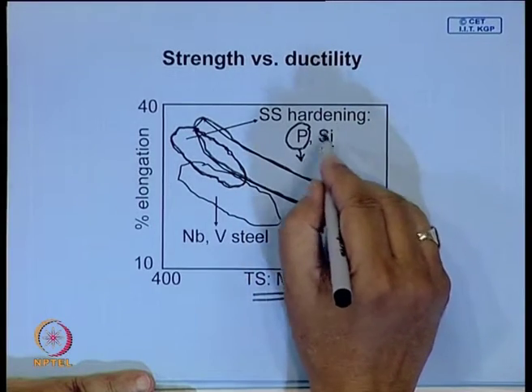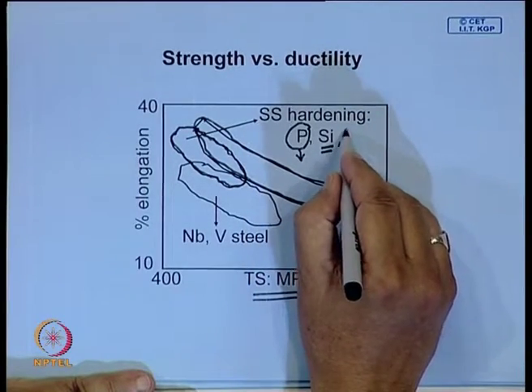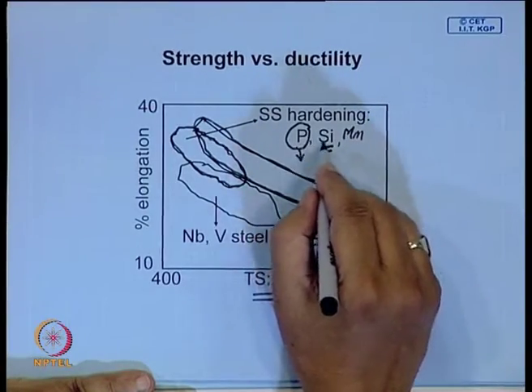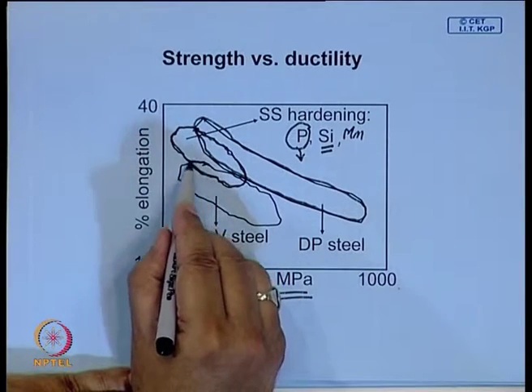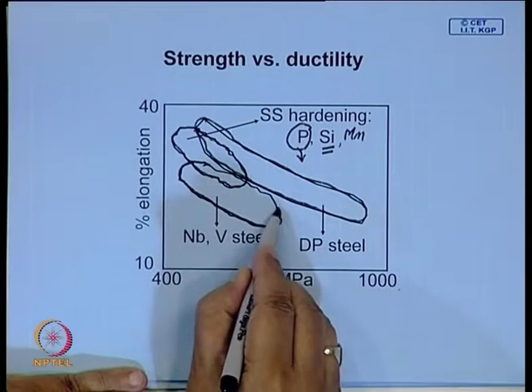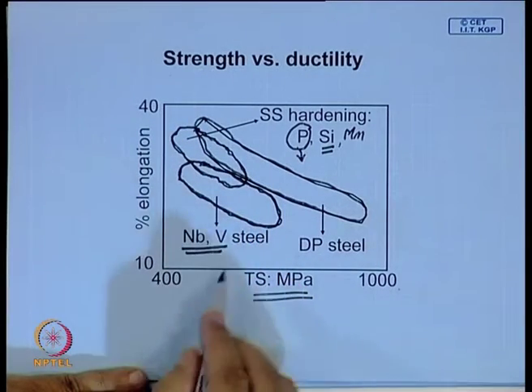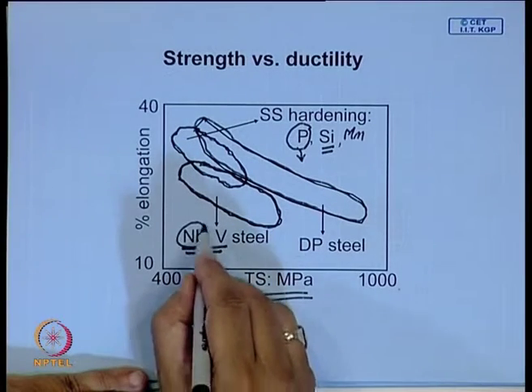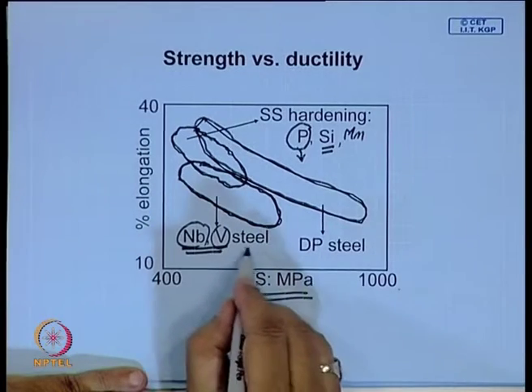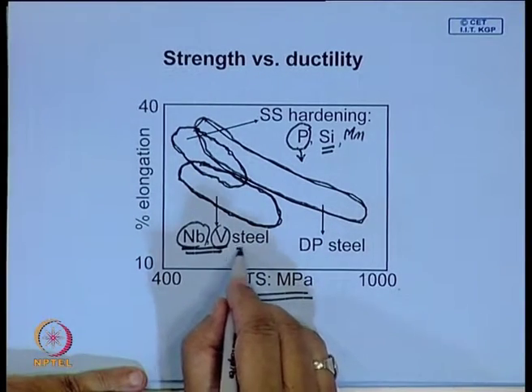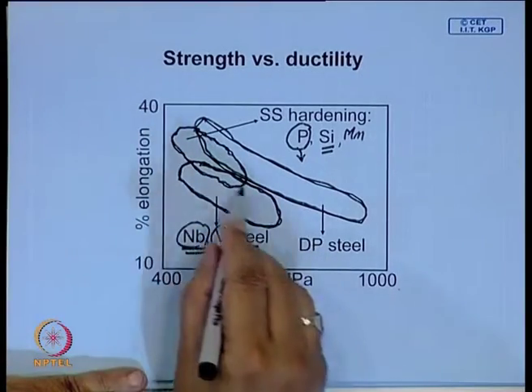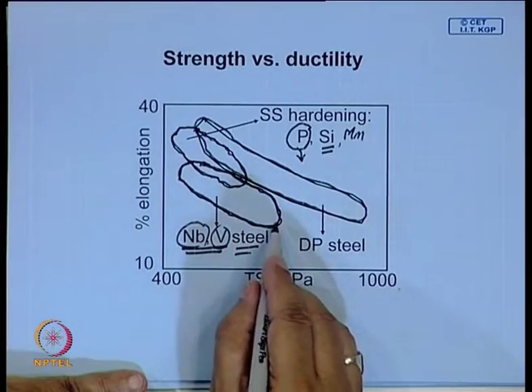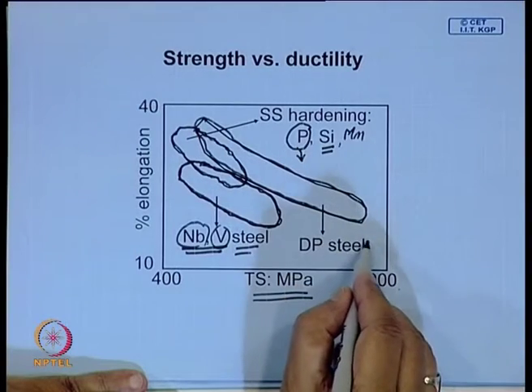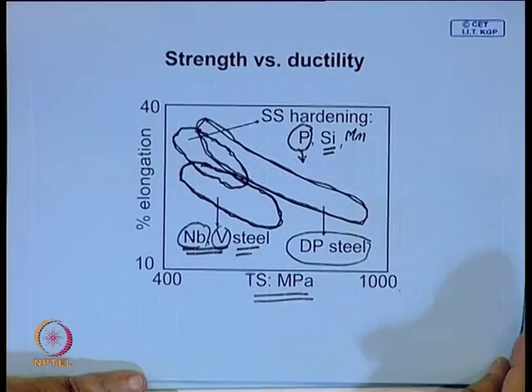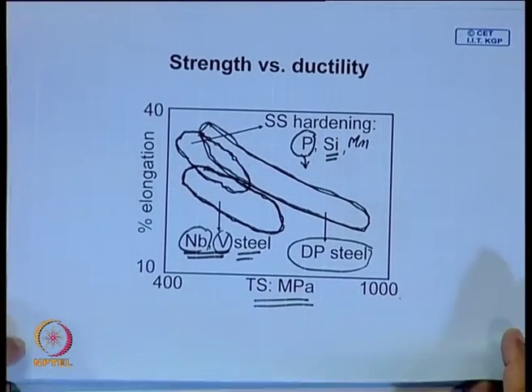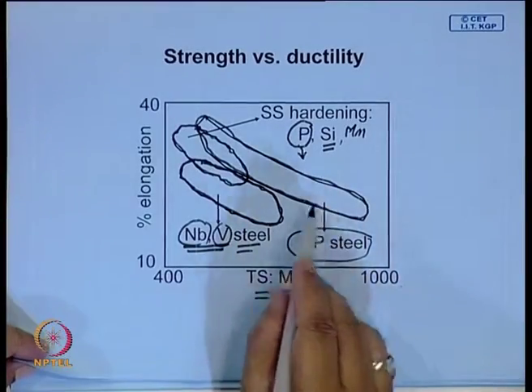Silicon is a common solid solution strengthener. Manganese of course does improve strength, but it is not as strong as phosphorus or silicon. And grain refining is the key strengthening mechanism in microalloyed steels, where we looked at grain refinement critically. Niobium and vanadium carbides and nitrides are the key constituents which inhibit austenitic grain growth, and you get a very fine structure. So, compared to all this, dual phase steel has a better combination of strength and toughness, and it also has good formability. That is why there is a special attraction for dual phase steel.